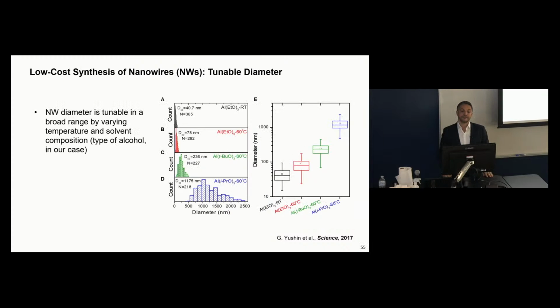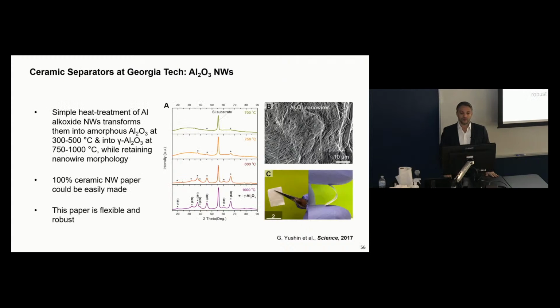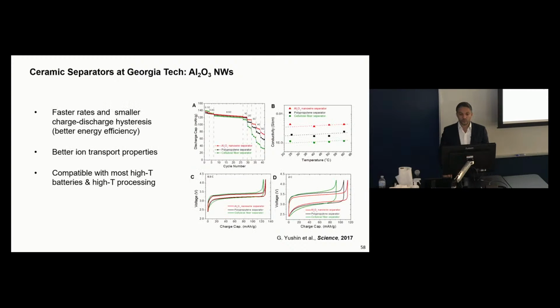And once you have the process, then you can choose different alcohols, different alloys as well, and you can tune the diameter of the nanowires. And by defining the size of the initial particles, you can also define the dimensions of the nanofibers. And so you can produce pretty long fibers with tunable dimensions. And if you have these alkoxides, you can also very easily convert them to a variety of other materials, such as oxides, simply by heating them up. They have a very nice conversion.